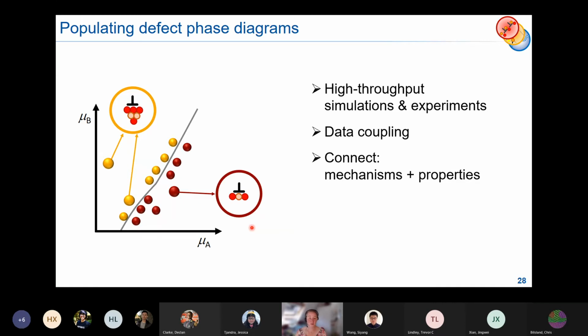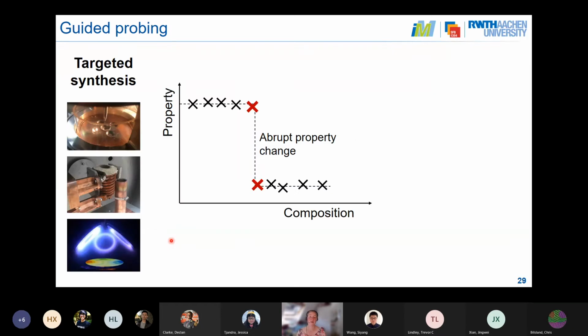We have a strategy for actually populating these defect phase diagrams. One of them is that we do targeted synthesis and that we don't look everywhere, but you kind of do the same strategies as you otherwise have. We think that most of the time when we get a change in defect phase, we'll also get a change in property. That could be the hardness, that could be the structure, and we'll be able to have fast techniques like, for example, indentation for hardness to look for property change.